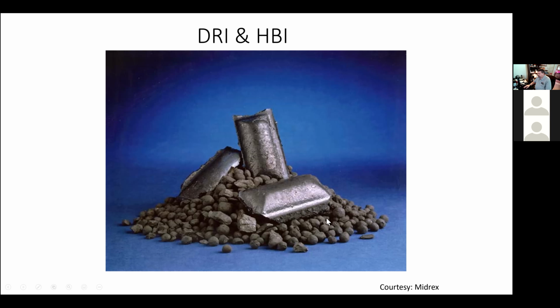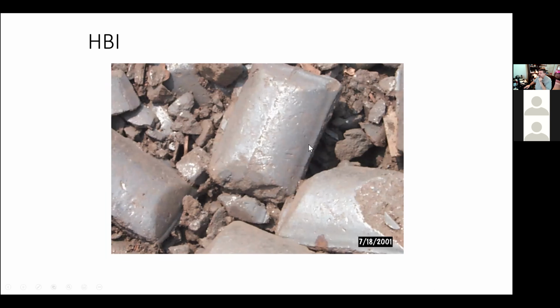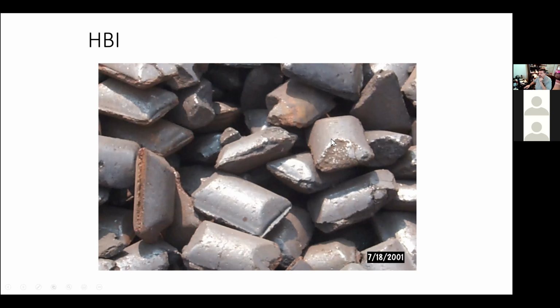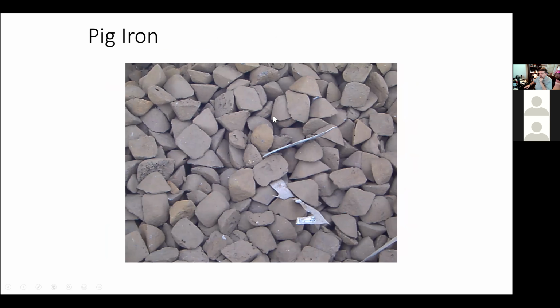And because these materials are based on iron ore, then they have very, very low contaminants with respect to residuals. And so we can add this material along with other steel scrap that we want to recycle that has a higher residual content and still meet the requirements for higher quality products that require very low residuals. This just gives you a few photos. And the other thing that we'll use sometimes is pig iron.